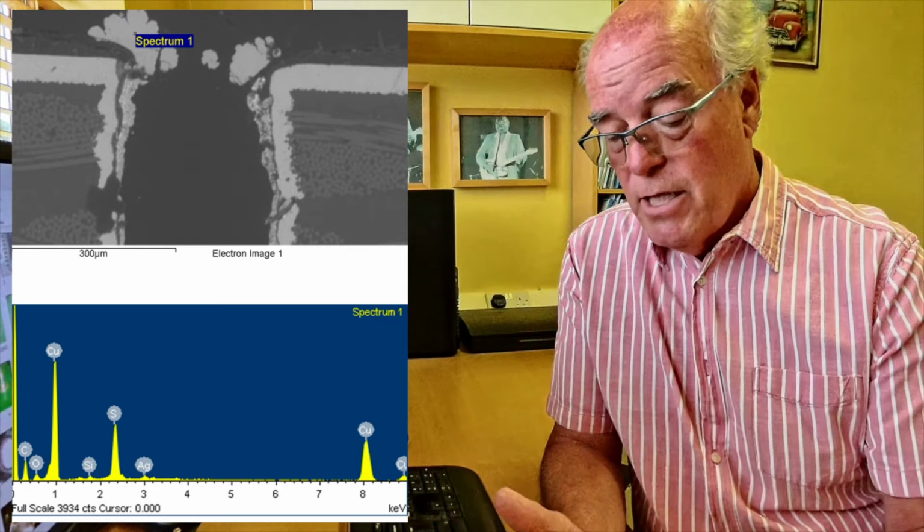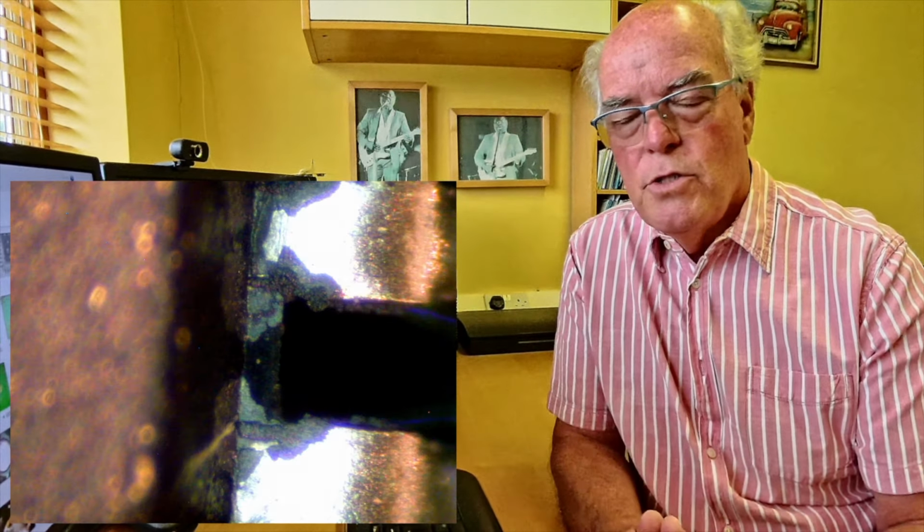I've experienced failures on resistors, but I've also seen it on other packages, and here's an example where you can see the exposed copper surface where you've got this form of corrosion present. In determining root causes, if you've got a sulphur-laden environment or packaging materials, a classic example I've had is foam packaging within an assembly which was put there to reduce the possibility of damage during vibration or shock or bump of that particular product.